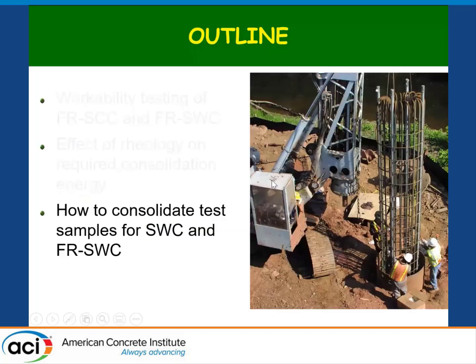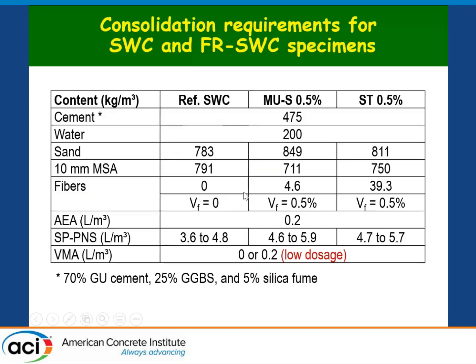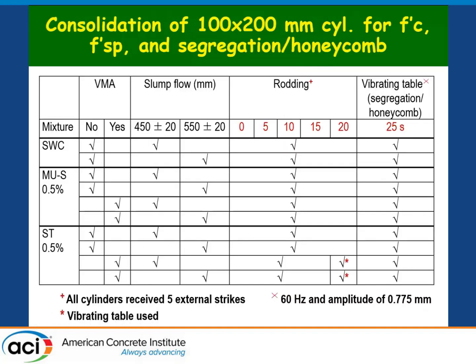And finally, for practical purposes, we wanted to know, well, when you are making samples, what kind of consolidation requirement you need to make test samples. So we took some super workable concrete and we prepared them using synthetic fibers and steel fibers. And then we change the fluidity. So for each of them, we have multiple mixtures. So we tested super workable concrete with 2 levels of slump flow, on the lower end of the super workable concrete and on the higher end, and then with and without VMA for stability purposes. And then we prepared our samples.